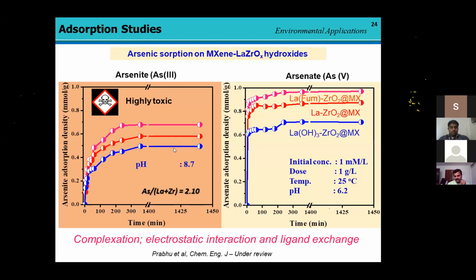Then we started with arsenic, since groups like hydroxide and oxide on the surface of MXene material will be more helpful for adsorption of arsenite and arsenate. We started with different lanthanum and zirconium composite forms of MXene. We purchased commercial lanthanum hydroxide and zirconium oxide, which were intercalated on the MXene phase. It showed lesser adsorption capacity compared with other forms. Another lanthanum zirconium form, synthesized by a simple one-step, one-pot method on the MXene moiety, showed higher adsorption capacity than the commercial phase.